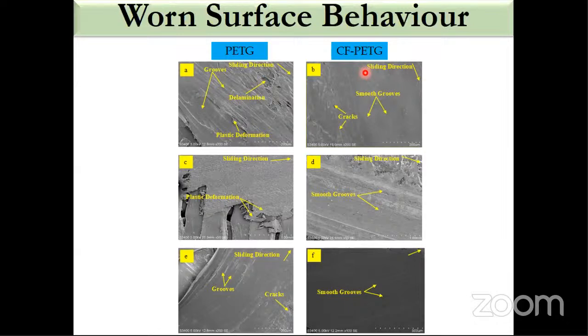From the worn surface analysis, we could see that carbon fiber reinforcement is actually helping in reducing the wear. Particularly smoother grooves were observed in the case of carbon fiber reinforced PETG. And we could see that no heavy plastic deformation, no plowing marks are visible in the carbon fiber reinforced PETG, which confirms the coefficient of friction results which we are getting, because of the tribofilm formation capability of carbon. So we could conclude from this study that the coefficient of friction is reduced because of carbon fiber addition at all loads and speeds. And this is happening because of the intrinsic lubricating nature of carbon and the film formation capability of carbon.